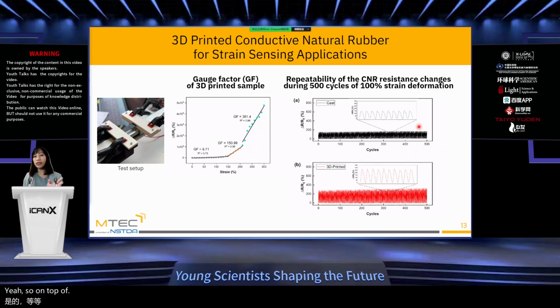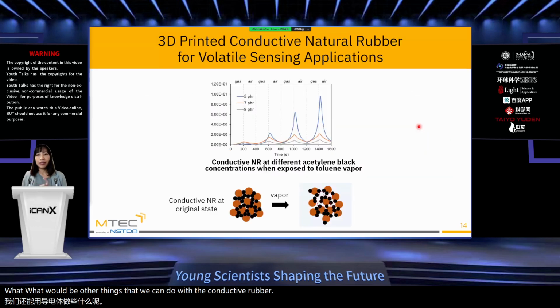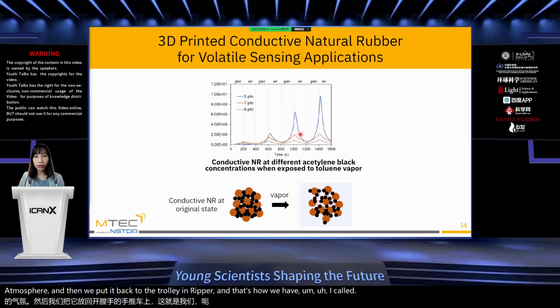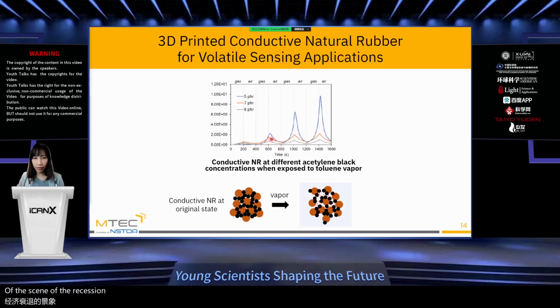Yeah, so on top of that, strain sensing is one thing. We made it possible. What would be other things that we can do with the conductive rubber? This is what we did. We used the same material, but this time it can sense gas. If you look at the plot here, we exposed this material to toluene vapor, and then we bring it back to the air atmosphere, and then we put it back to the toluene vapor, and that's how we have a cycle of the change of the resistance as shown here.